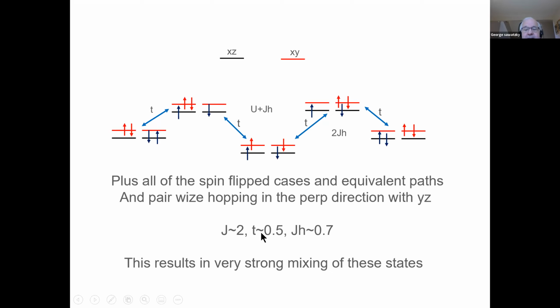And you see that if you multiply this hopping integral here by the degeneracies that you have, or by the square root of the degeneracies of what it can hop to, that's basically what you have to do. Then that easily multiplies this by at least a factor of 2 or 3, right? And then everything is of the same order of magnitude. So everything is mixed together very, very strongly, okay? And then you have basically a reduced magnetic moment on each atom. And the reduction of that magnetic moment is going to be extremely sensitive to the parameters.